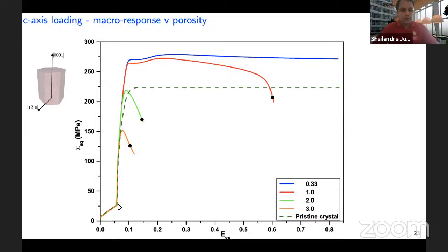If I talk about this yield stress, where the stress suddenly shoots up, and the saturation stress, we find that there is a certain critical ratio of these two stress levels, beyond which your material will transition from ligament necking to ligament cracking, and essentially cause a brittle type manifestation of fracture. It will suddenly fracture rather than show a more graceful coalescence phenomenon.